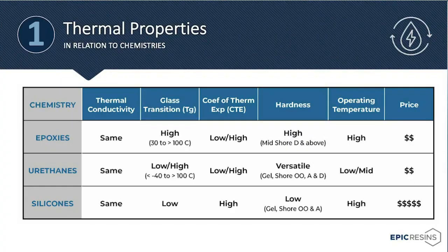So when we discuss epoxies, urethanes, and silicone potting chemistries under thermal conductivity, ultimately all of these chemistries can have the same thermal conductivity, because that thermal conductivity primarily comes from the type of raw materials that we use in the potting material. So when we compare epoxies, urethanes, and silicones in glass transition temperature, epoxies have the highest glass transition temperature possible for these three chemistries. And this comes from the cross-link density that polymer has.